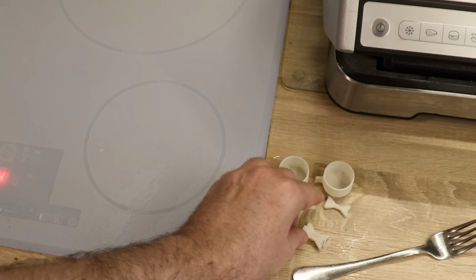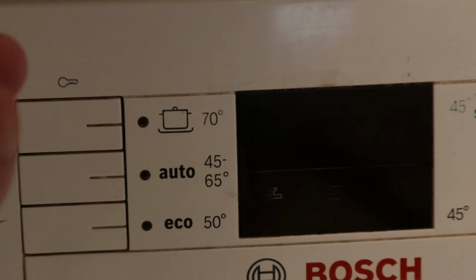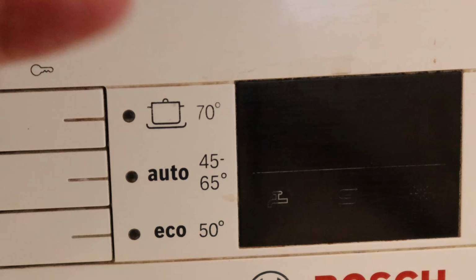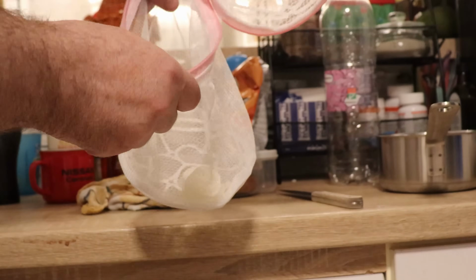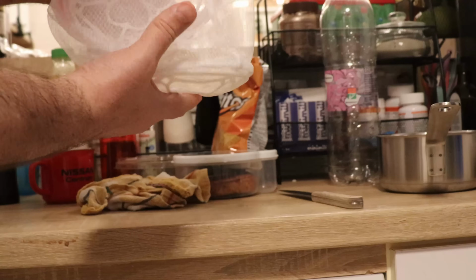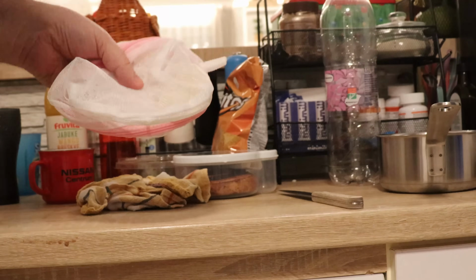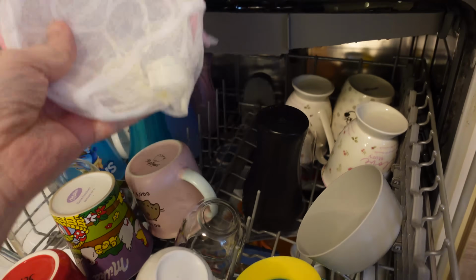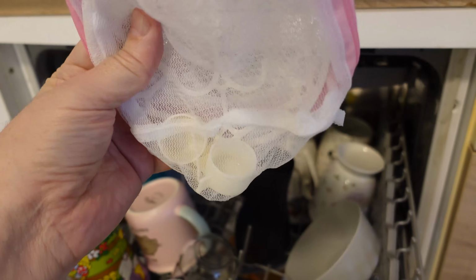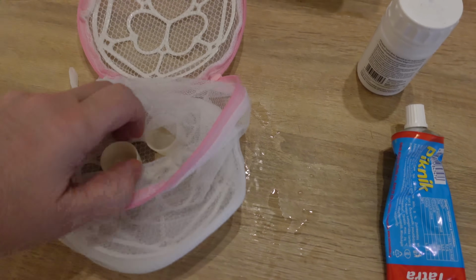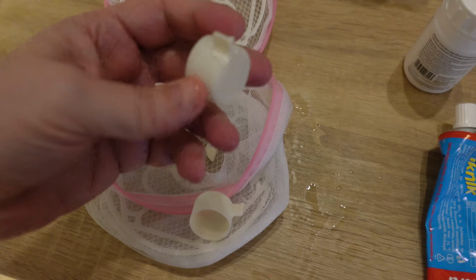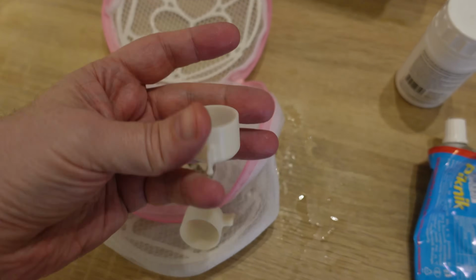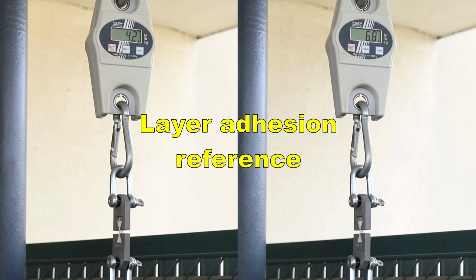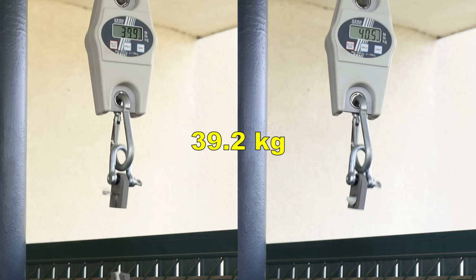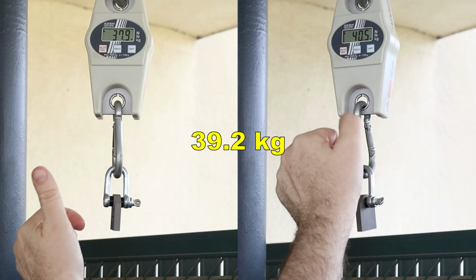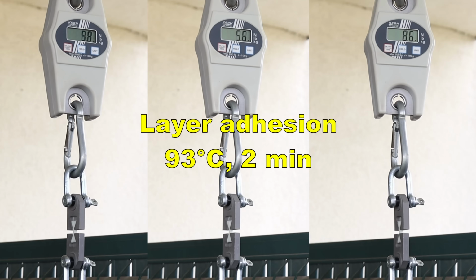Objects are marked, and now we have another cleaning method, the dishwashing machine, 70 degrees Celsius. And I have this net, so I can place these small test objects into the machine. They are still in one piece. After the washing, visually there is no degradation or deformation on the objects. But let's measure the layer adhesion. Reference without any cleaning. Cleaned in almost boiling water.